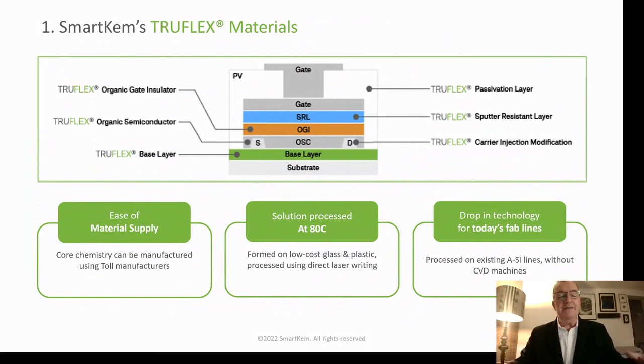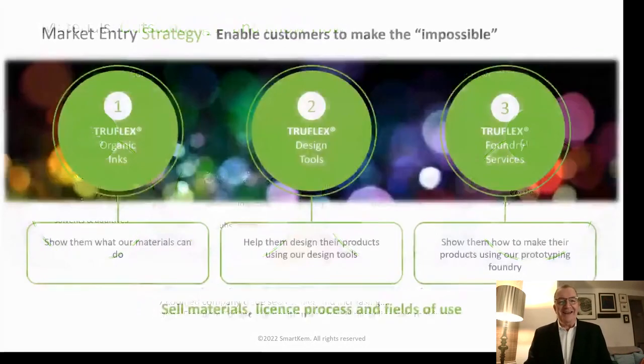We make a base layer, organic semiconductors, gate insulator, sputter-resistant layers, and passivation layers. What's unique about what we do is we do this as a solution process, but we do it at 80 degrees centigrade. And that means that we can do it on low-cost glass and plastic, and it's a photo curing process, which means that we can pattern them using direct laser writing. And they've been designed, even though they're organic materials, to be able to be processed on amorphous silicon lines. But of course, we don't need the high energy consumption machines, the PECVD machines. And you can look at the know-how at a different time.